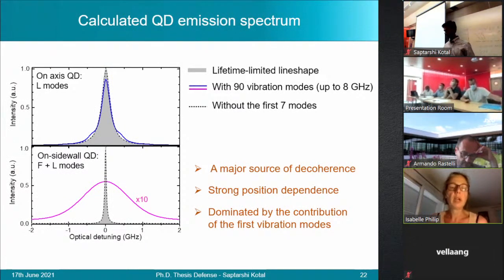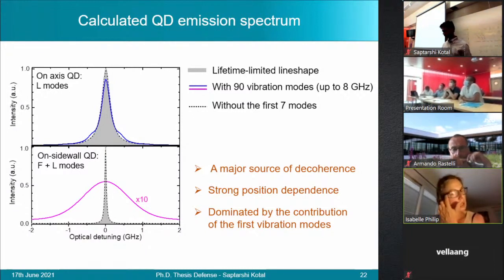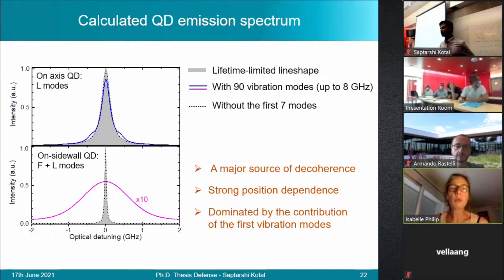Then just for curiosity, on slide 22, we see that if we look at the line width, whether the dot is on axis or off axis, you don't see much change because they are both broad, but for different reasons. For the on-axis dot, this is due to the lifetime shortening, due to the Fermi golden rule, and you have an enhancement of the local density of states, whereas in the second case, this is due to the coupling to the phonons. So have you tried to check the different lifetimes to corroborate that in the structures that you have, if you have this dispersion in lifetime, though a rather equivalent line width for all the dots?